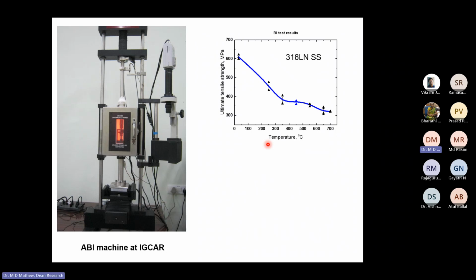So at IGCAR, as Dr. Reddy knows very well, we had a big research program on developing low carbon nitrogen alloy 316 stainless steel for certain important applications in fast reactors. As part of the development of that material, we have done a lot of experiments using this ball indentation machine. What you see here is the variation of ultimate tensile strength as a function of temperature based on the ball indentation tests that we have done. As expected, you see that the UTS decreases with increase in temperature. And these tests were carried out all the way up to 700 degrees centigrade.